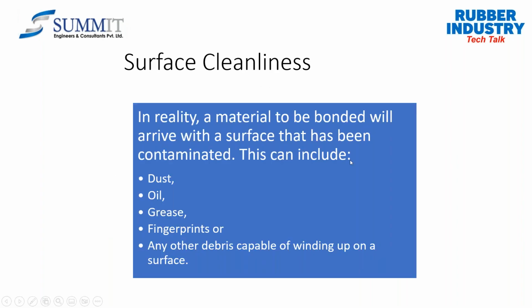Now, the surface cleanliness is a very important perspective for the dry film lubricants. In reality, a material to be bonded will arrive with a surface that has been contaminated. This can include dust, oil, grease, fingerprints, or any other debris capable of winding up on a surface. Especially for the rubber or the metal, whatever type of components you are considering, it is required to be pre-treated. The cleaning could be just by way of hot water, by conventional water rinsing or soap alkaline cleaning. A variety of processes are there, right?